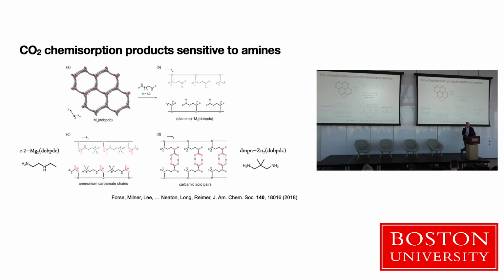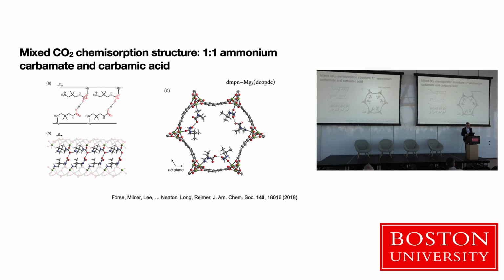There are just a few more slides here, but basically the first thing I wanted to tell you, to help you follow what I'm about to say, is that there are multiple ways CO2 can bond to an amine-appended MOF. One way, if you like Lewis structures, is this cooperative chain formation along the pore axis. But actually CO2 could also attack this nitrogen, and as long as there's one up here, then there's another stable structure, which is a carbamic acid structure. And depending on the topology of the MOF pore and the nature of the amine, you can get either the chain or the carbamic acid. And you can even get both. You can get a mixed regime. So it's kind of fun.